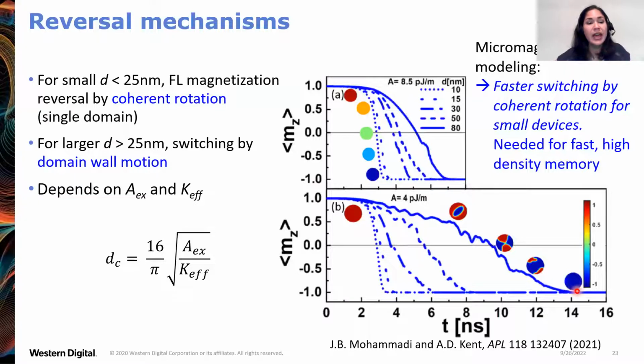And you can see that domain wall reversal takes longer. This y-axis here is time. It takes longer than coherent rotation, and it especially takes longer if you have a free layer material with a low exchange stiffness A compared to a free layer material with a higher exchange stiffness A. So for this reason, if we want to have a fast and high density memory, we need to be in the reversal regime where you have small devices where the free layer flips by coherent rotation.